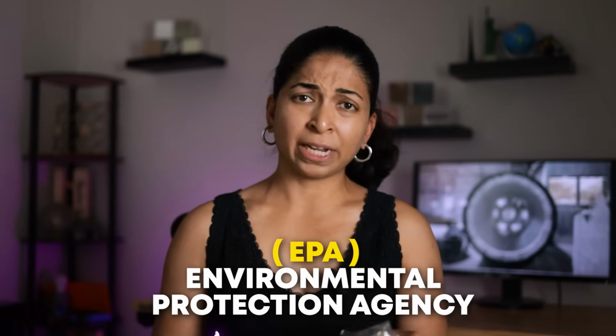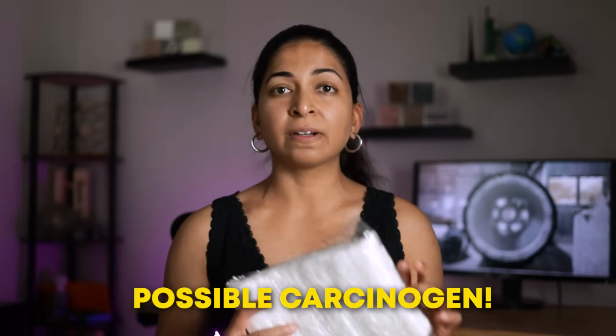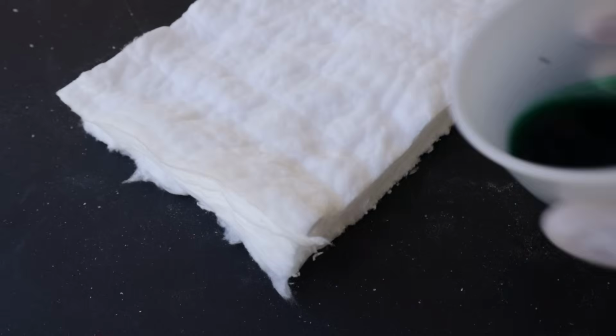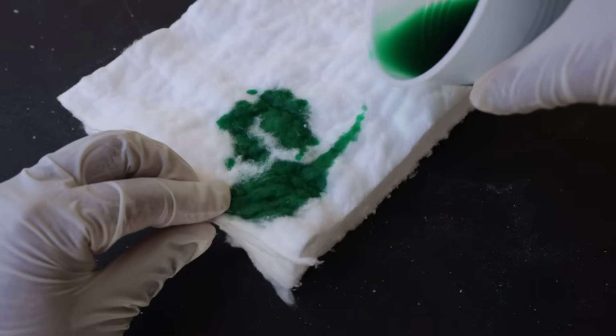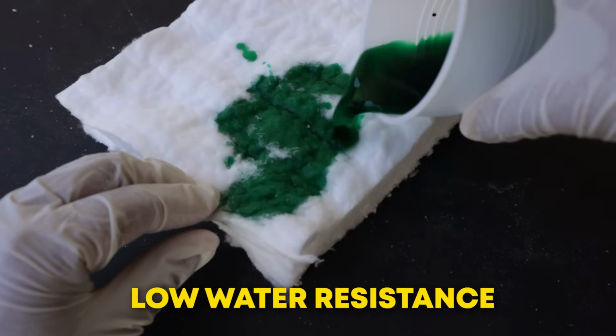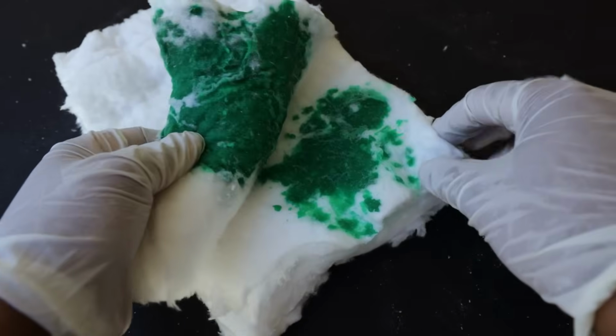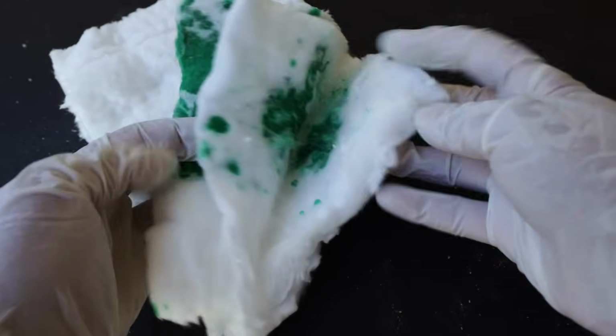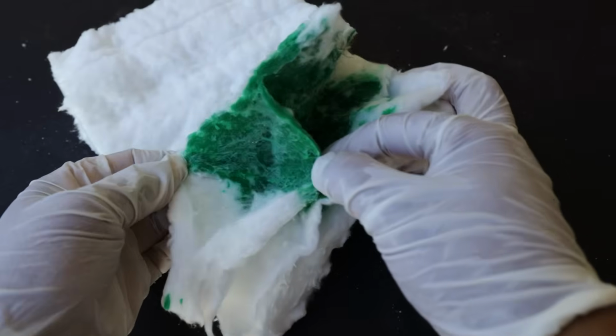Moreover, the Environmental Protection Agency, or EPA, classifies ceramic fibers as a possible carcinogen. Prolonged and repeated exposure to this fiber dust can cause cancer and lung damage. For these reasons, ceramic insulation is mainly used as pipe insulation in commercial settings where pipes are exposed to extreme heat. This kaowool insulation also has surprisingly low water resistance. As you can see, water soaked right through all the layers of the material. It immediately compressed and lost its shape.